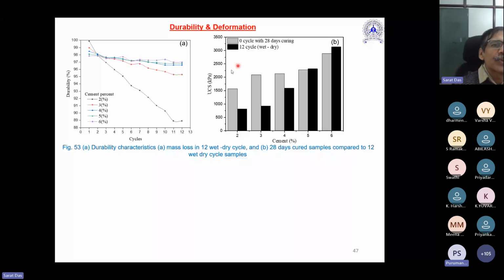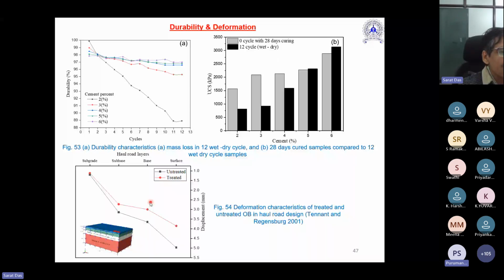So for this you have to do 12 wet-dry cycles, and you see when I am going for 5%, mostly the values compared to the 28 day cycle curing, these 5% I can consider because there is almost no reduction. Otherwise, at 2, 3, 4% there is reduction in strength with alternate wet-dry cycles.